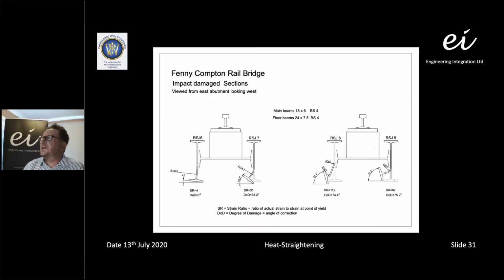So again, I think we've shown that slide before. Therefore, you can see the rotation of the girders and the respective strain ratios associated with the rotation of the girder. We in the UK are limited to allowing a strain ratio of 50. Anything above 50, the Highways Agency at the moment won't allow us to heat straighten above that point. So therefore, we're limited to an upper strain ratio of 50. In the United States, they've allowed contractors to take the strain ratio beyond 50, and they're working with strain ratios up above 150. So they're pushing the boundaries far more than we are doing in the UK.